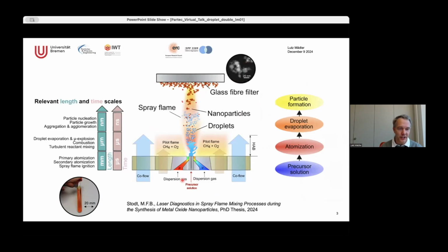And these reactors are so-called spray flame reactors. So it's a spray where you have liquid, this kind of liquid, and you disperse that with some dispersion gas. Most of the time it's oxygen, and you disperse that into very fine droplets. And these fine droplets you ignite with what we call a supporting or pilot flame. Here is methane oxygen. It can also be hydrogen oxygen. And that provides the heat to ignite these droplets. And these droplets, they burn on their own. So basically this liquid here is combustible.